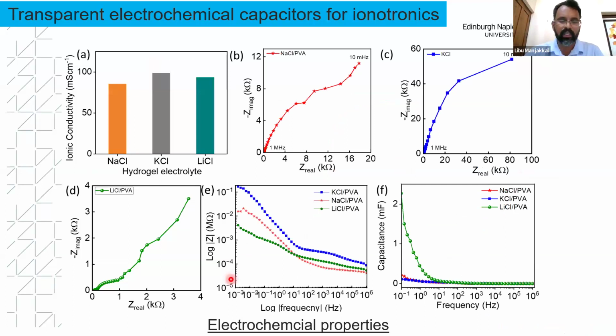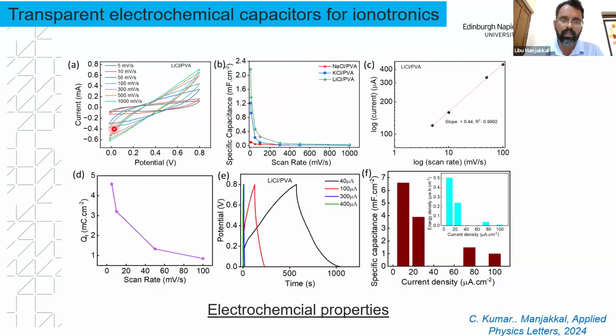Then we did the electrochemical study of the sensor. As you can see here, the ionic conductivity of the gel electrolyte, and then we measured impedance spectroscopic analysis of the devices. We found that the lithium chloride-based gel electrolyte shows a very low impedance value and better performance, with a high capacitance due to the high ionic conductivity or high ionic strength in the device. Then we measured the cyclic voltammetry to see if there is any strong redox reaction. We didn't find any strong redox reaction, but there is a pseudo capacitance because of the ITO, the metal oxide.